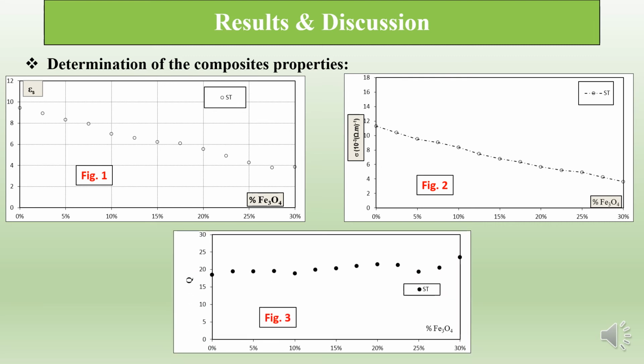And figure 3 shows the quality factor evolution of composites as a function of the iron oxide volume fractions. From the graphical results examination, we note that the values of the quality factor obtained vary between 18.5 and 23.5, which explains the drop of the dielectric tangent losses varying from 0.05 to 0.04 for the composites. The values obtained are relatively large, which allows maximum energy storage and the least dissipation possible.